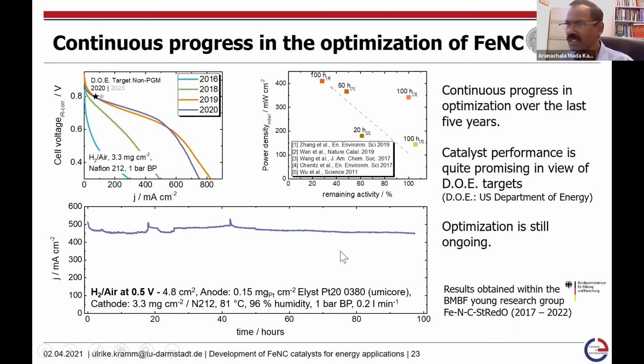Did you do any real long-term testing? Because 100 hours is probably not really long term, right? For this catalyst, we also went up to at least 200 hours, and it looks quite stable. It depends, of course, on what you call stable. But if it loses only something like 10 to 15% within 200 hours, I would call this relatively stable for an FeNC catalyst material.